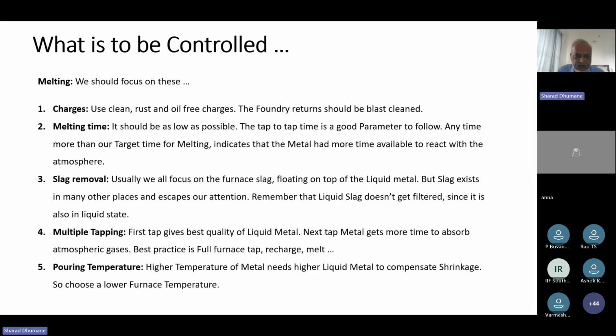For example, if your control plan says that you will tap at, say, 1560 degrees centigrade, because you are pouring some particular casting which has thin sections and you want your pouring temperature at the mold spout to be something like 1420, 1450, so you choose your tapping temperature about 1550, 1560. But then you see that it doesn't exceed 1560. It doesn't become 1570, 1580. Because if it goes to 1570, 1580, then you know that more liquid slag must have formed, and you run into quality risk. So pouring temperature is another control point in your hand, which you can control rigidly, strictly, and maintain your controls on melt quality.